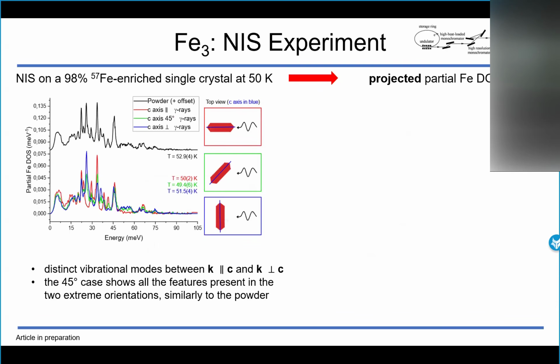And then we have the really core measurements, the core nuclear inelastic scattering measurements that were realized on the single crystal of this spin triangle. What we can see now is the projected partial iron density of states. Projected in the sense that each phonon is weighted by its projection on the direction of the gamma ray wave vector. In fact, we did the experiment in different orientations.